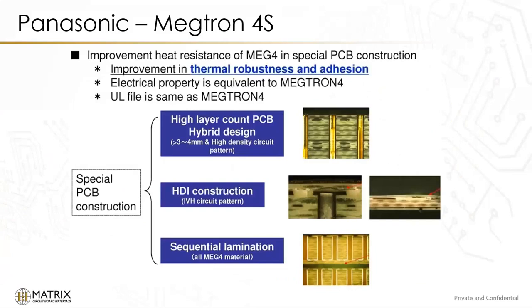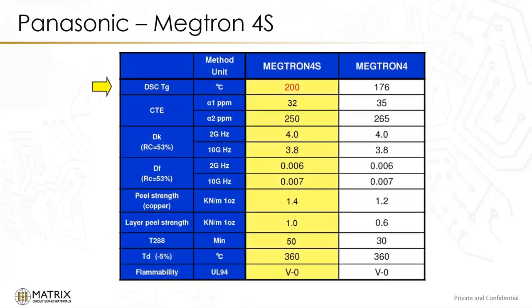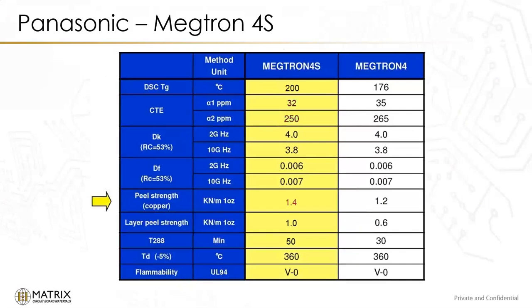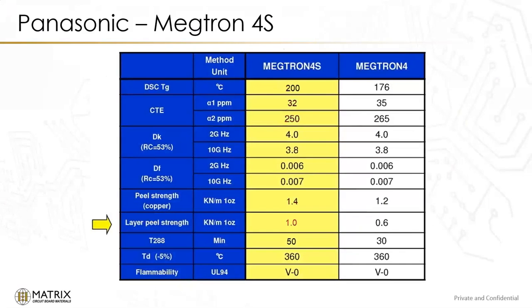So 4S addresses that, and it does that by improving, like we said, the thermals. As a result of pre-reacting the components, we get a higher TG. It's a 200 TG. The Z-axis CTE is improved, lowered. We have actual peel strength improved. The interlaminar bond is improved, which is a key to that. We get a T288, that's a higher number. And the electrical properties are the same because it is the same product.